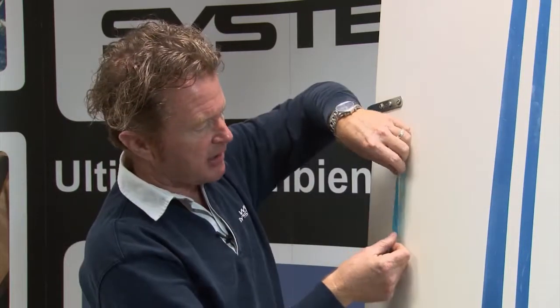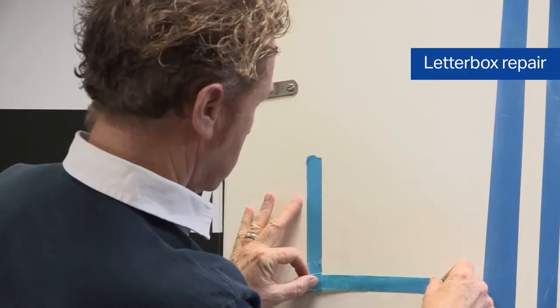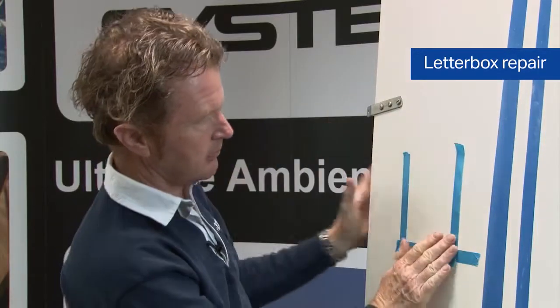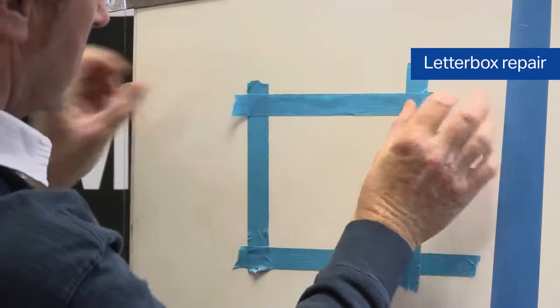I want my backing plate to be at least the diameter and a little bit more of the hole that we've prepared, because we actually call this type of repair a letterbox repair. Now, of course, to manufacture our backing plate, I need to be able to release it away from the existing hull. And to be able to release it, I need to use some release wax. This is a dedicated mould release wax produced for GRP moulding work, but actually Simoniz wax will work perfectly well, Simoniz in the yellow tin.